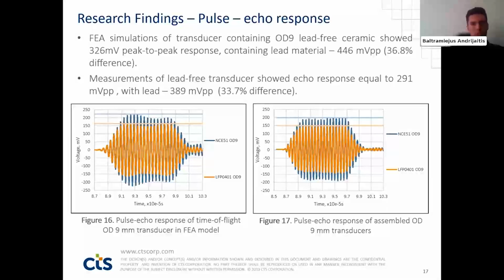Here, pulse echo response showed more similar results compared to simulations and assembled transducers. Difference in performance between materials is jumping around 35 in real case scenario and in simulation. So we get more constant values, which also was influenced by higher thickness to diameter ratio, I would say.